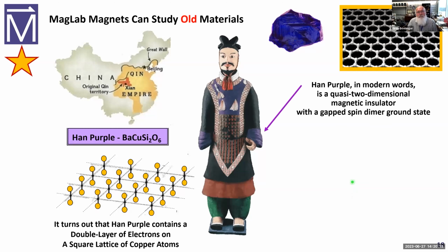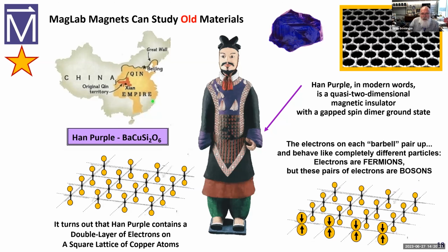And so, in modern terminology, Han purple is a quasi-two-dimensional magnetic insulator with a gapped spin dimer ground state. And we're pretty sure that they didn't know that in the Qin dynasty. And what happens is that the electrons on each barbell, the one in the lower layer and the one right above it in the upper layer, they pair up and they behave like completely different particles. Electrons are fermions. Each one has 1/2 spin, which is the smallest unit of magnetic field you can have. These electrons pair up and they save magnetic energy by anti-aligning their spins, and then they act like a single particle.